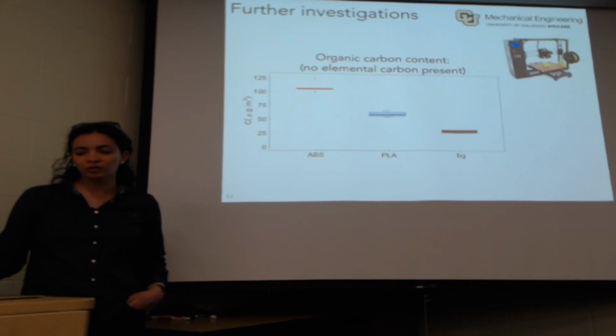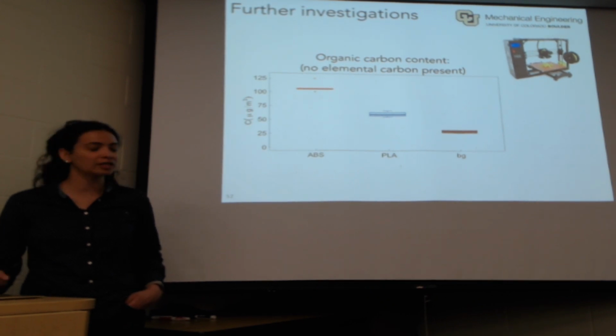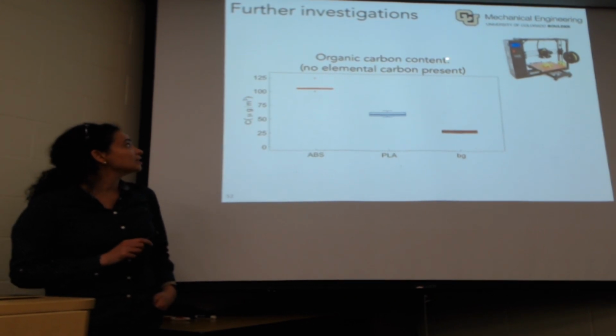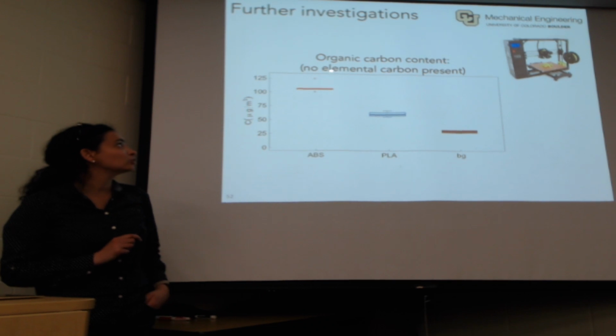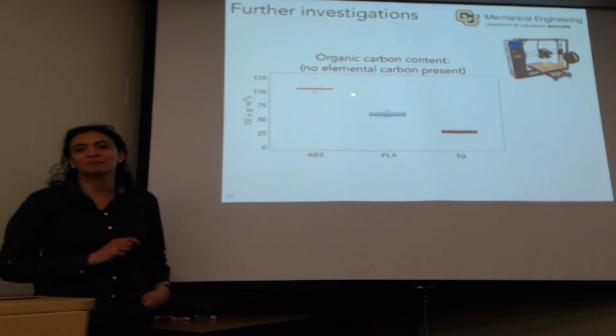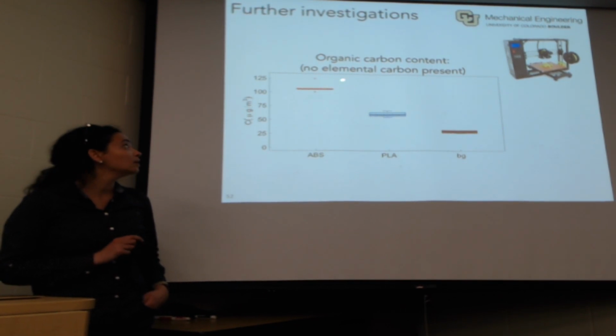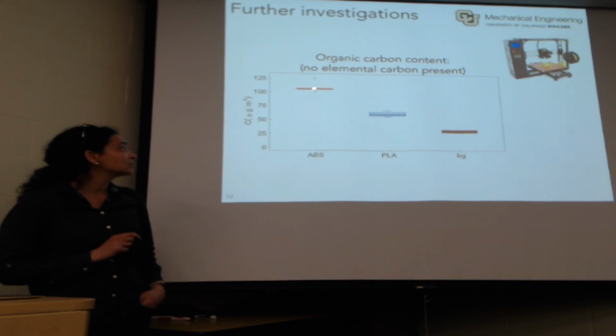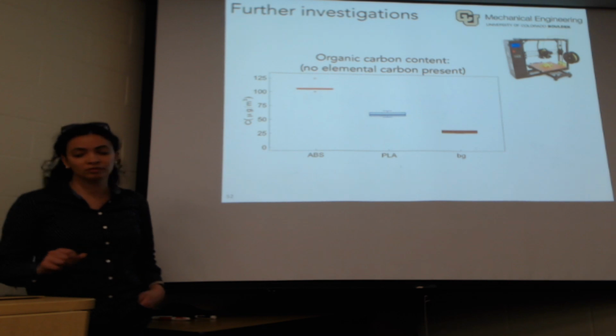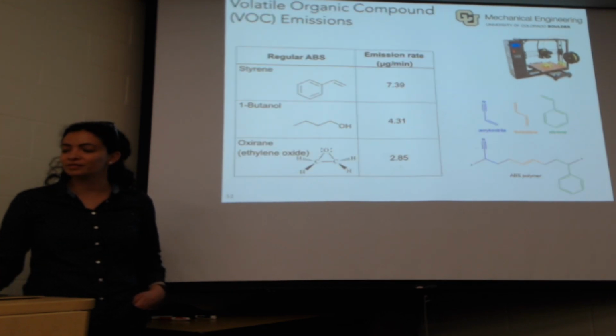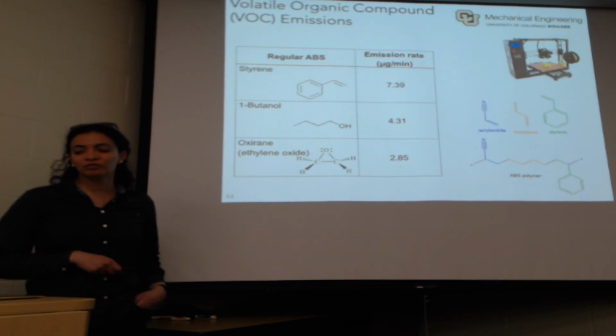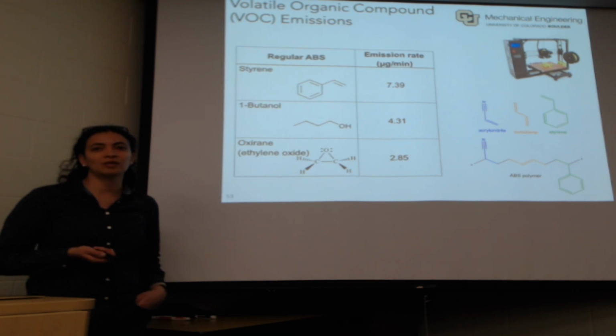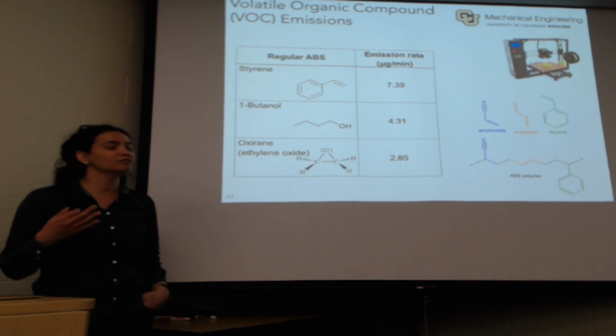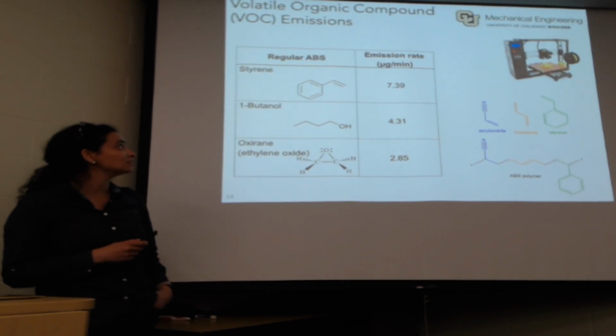So further work that we've been doing at CU Boulder is looking at the elemental carbon content. We found that there is basically no soot being emitted, as expected because the temperature is rather low. All of the carbon is organic. ABS emits a lot more than PLA, as we all know, and both more than the background, of course. And we've been doing some of our own VOC emissions testing and figuring out what's in the gas phase itself.